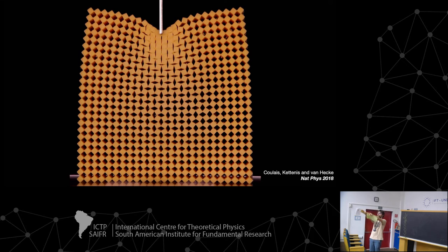So to lowest order, neighboring squares just counter-rotate. But then at some point, even though it's not been designed for that, it's perhaps preferential to rotate in the same direction or even stretch a little bit, right? There are multiple ways you could do that, but if you just add an energy scale that describes not the counter rotations only, but rotations in the same direction, then that's sufficient to explain the decay. And this decay length is exactly the ratio between these two energy scales, right?